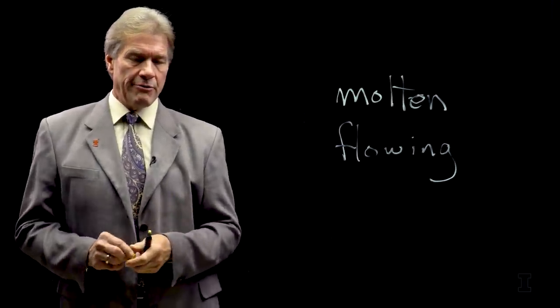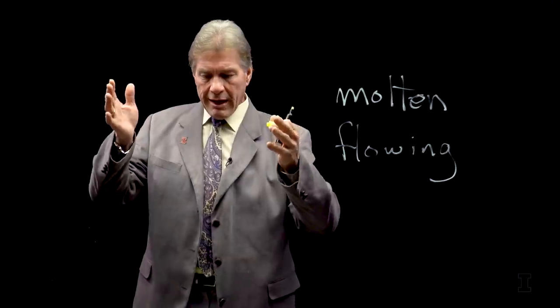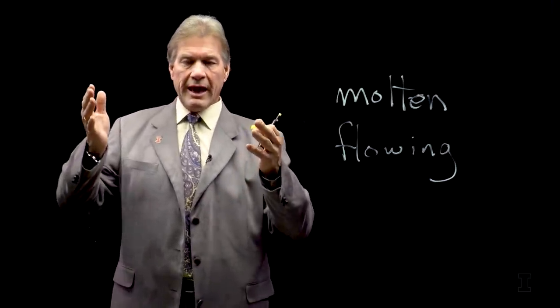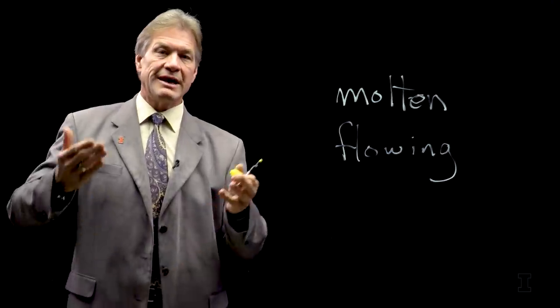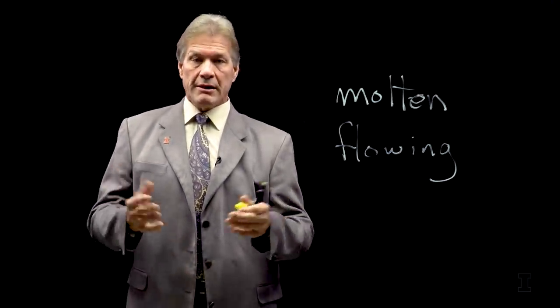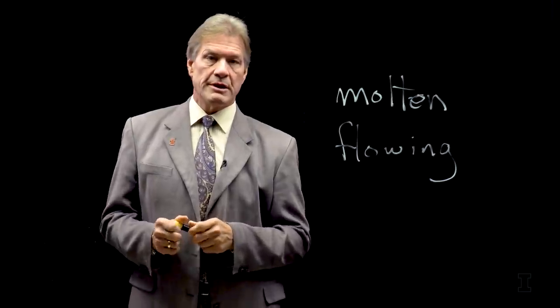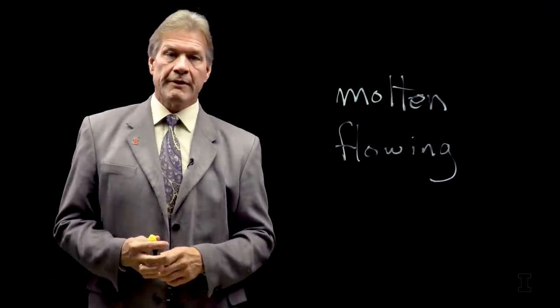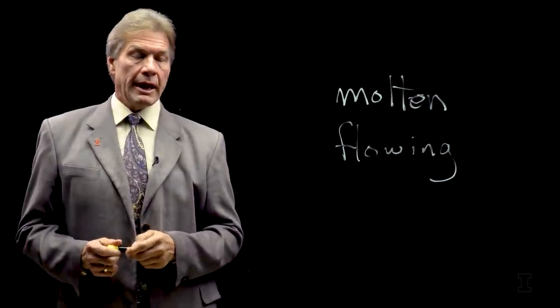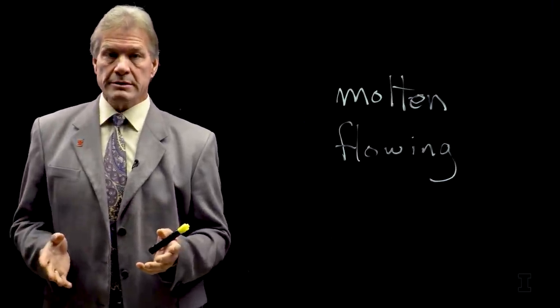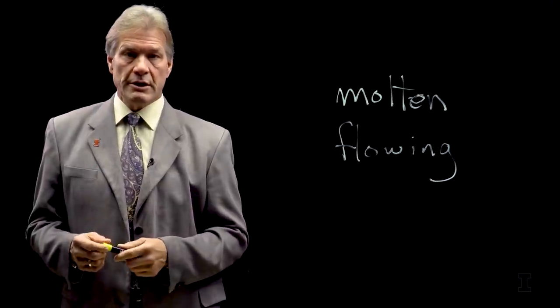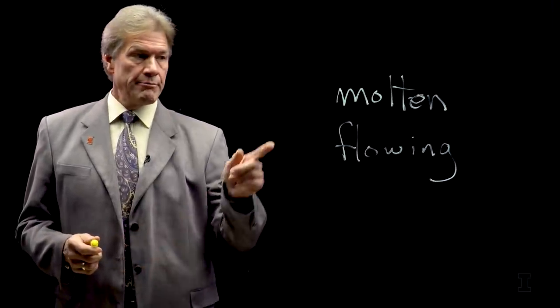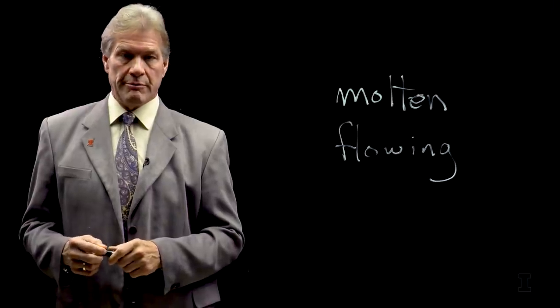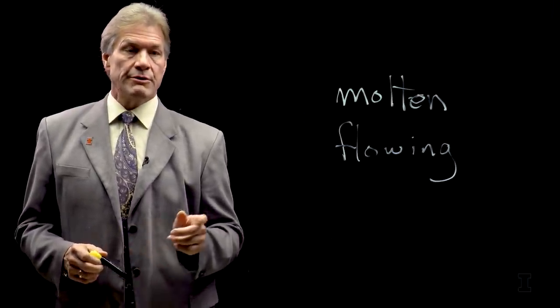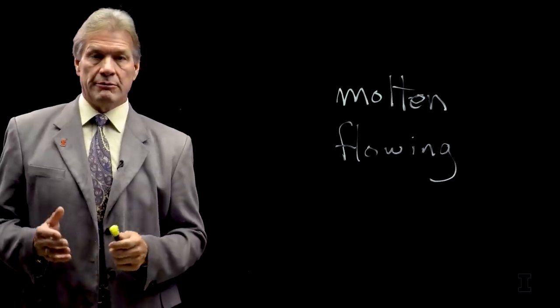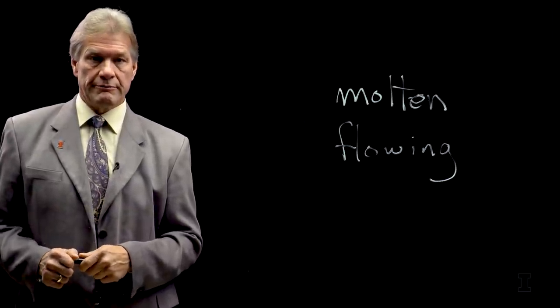So get this right. I want flowing liquid metal on the edge of the plasma. And it has to work, it has to keep going, it has to not contaminate the plasma. And can you do it? Can you find experiments? Can you figure out a way to do it? Well, we did. And it's just one of several different ways. It's the one we've been working on quite a bit ourselves. It doesn't mean it's the best way. But having flowing molten lithium in some manner at your device is going to give us this economic advantage that could allow fusion to actually be competitive.